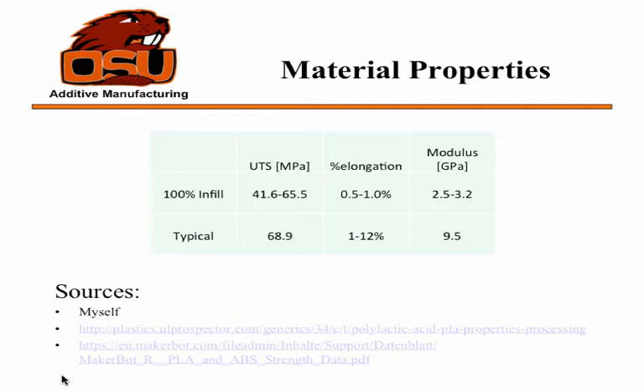And actually, MakerBot was useful and good several years ago before Stratasys bought them. They actually came to the conclusion that it is almost 100% related to how many outer layers you have. The infill has zero statistical effect on the overall strength of the part. And it's because the layers are not actually oriented in the direction of the way you're pulling it, so you just get a shearing effect that breaks everything apart. And shear strength is usually around half of what tensile strength is.